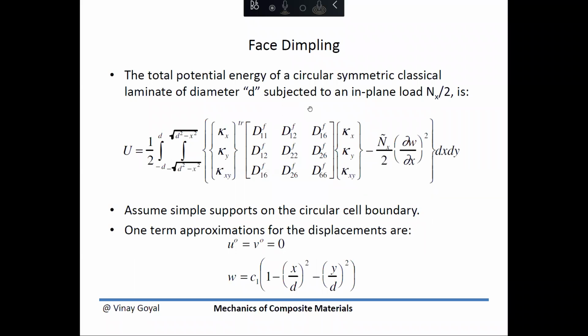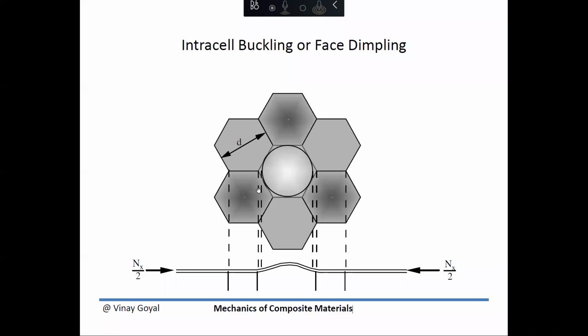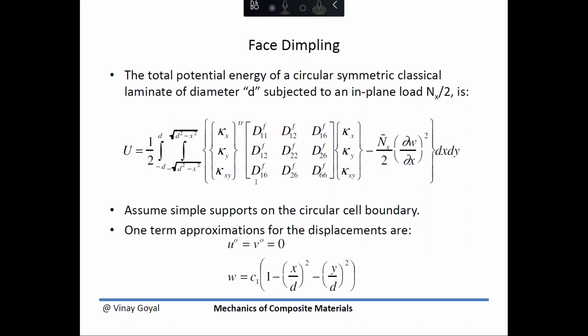We can also do a calculation of face dimpling using the total potential energy of a circular symmetric classical plate. Here, we're looking at this circle that is circumscribed into this hexagon. The idea is to see what compression loading can cause this circular section to buckle. So we've used the total energy of the system. We're going to make an assumption that the deflections follow this formula, and what we want to do is determine what amplitude can potentially buckle it.